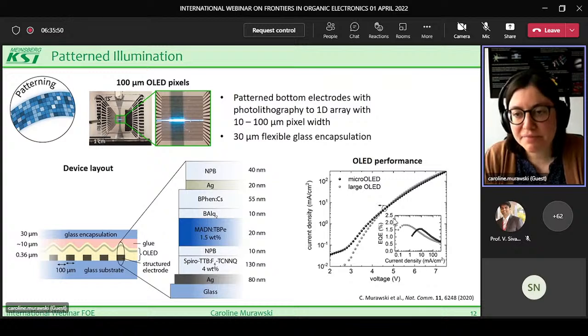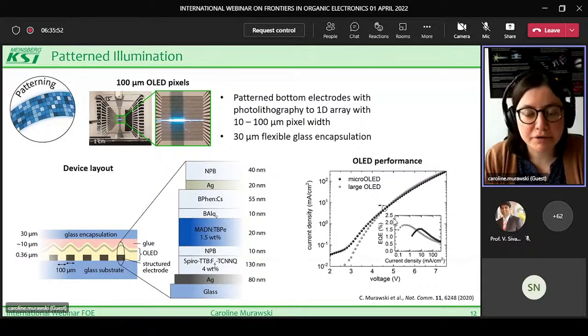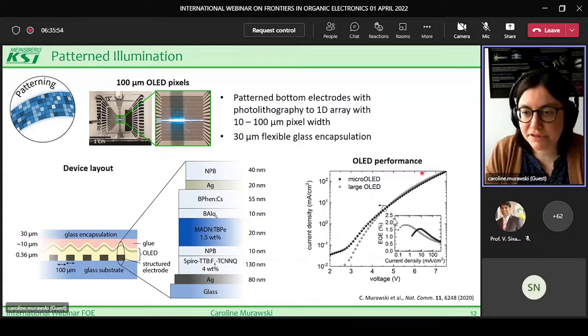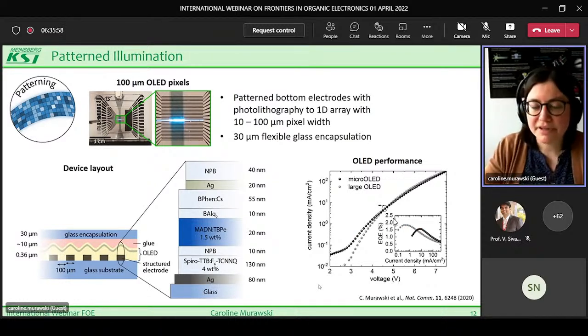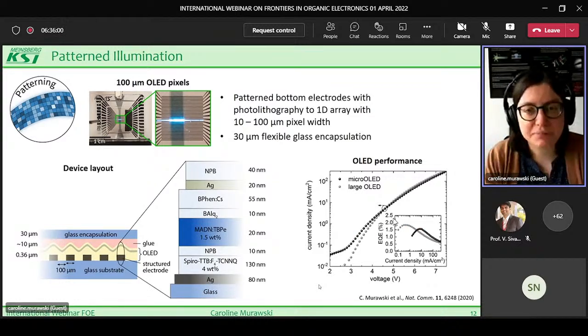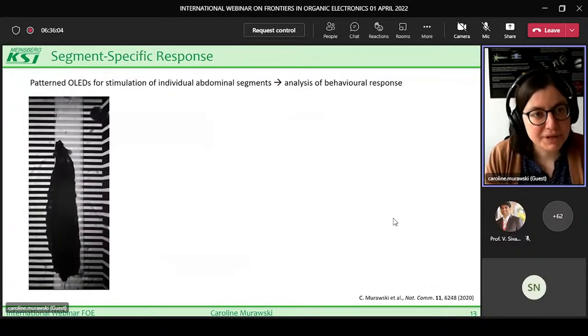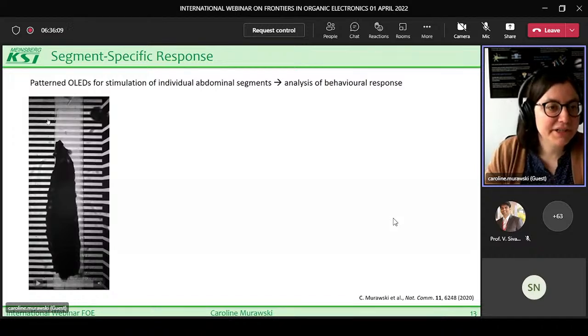The performance of these microstructured OLEDs is comparable to the large devices. So you see here the current density and the EQE of the devices. There's no significant change by this patterning of the bottom electrode. We applied this again for our Drosophila larvae, and what you can see now here is our OLED display